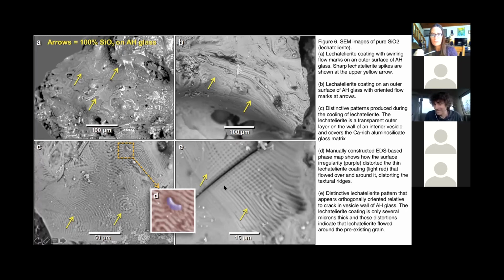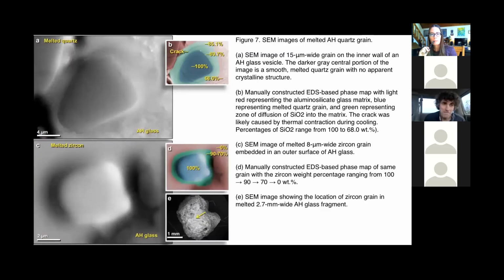So it showed some anomaly. And here is an interesting example where Lechatelierite makes a perpendicular kind of pattern versus this fracture in the glass. It's again some amazing image that I've never seen. And look at that, melted quartz. When you look at the sample, you can see this blob of something, then you measure the composition in the middle. Okay, it's quartz, but it's kind of weird. It doesn't have really good boundaries. But when you measure the composition away from it, you can see it's diffusing away into the glass. So you can see 100% quartz, and it goes less and less until it becomes the same composition as Abu Hureyra glass.